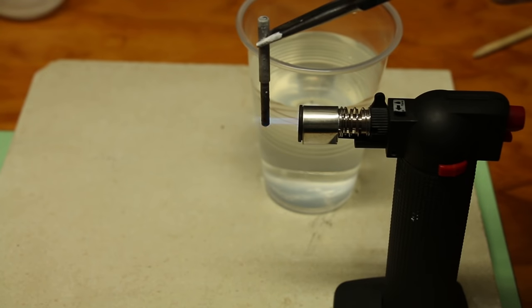When quenching the material, do this in an upright vertical position. If you come in sideways, it can bend your material, especially when working with fine diameters. If you were using water, ensure that you agitate the part when submerging.